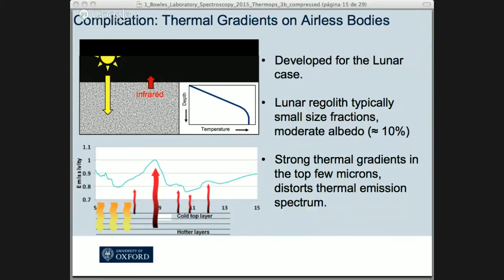What that then means is that shortwave radiation can penetrate deeper into the regolith, maybe a few hundred microns to a millimeter or so, and warms the subsurface layers, makes them slightly hotter, and that's the region that we then start to probe. It's a bit like a greenhouse effect type thing, but for rock or mineral powders. That starts giving you more energy. So you end up with an effective emissivity, which we normalize to 1 at that point, which is then higher than the rest of the spectrum.